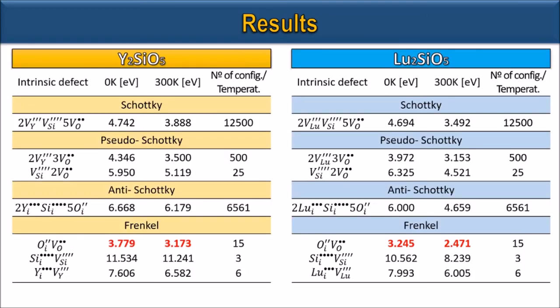So, the lowest solution energy for each type of defect calculated for each structure is presented in this table, as well as the number of different configurations that were calculated. It is interesting to note from this table that when increasing the temperature from 0 to 300 Kelvin, all the solution energies decrease, and for the oxygen Frenkel defects in lutetium silicate, the reduction was around 24%.